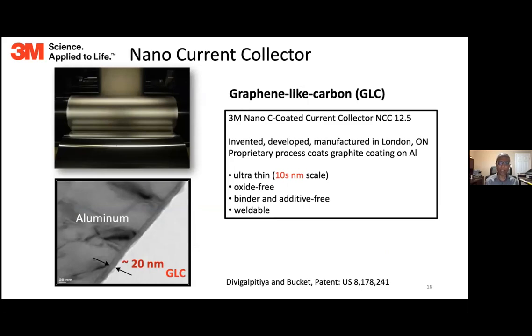So this works really beautifully. I call this material graphene-like carbon because it's not pure graphene, but it's pretty close to graphene in the performance. And it's also close to graphene in the structure. It's only 10 nanometers thick. Once you put it on aluminum or copper, it protects the battery and makes the battery last longer, and makes the battery lighter as well, because people were using very thick carbon black coatings before that, 100 times thick. We used to manufacture and develop this product in London, and we are manufacturing it here as well.